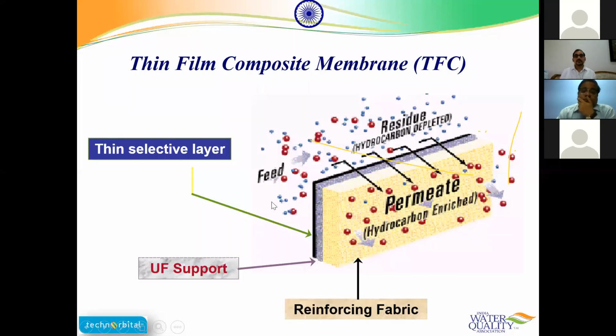Then we have a thin film composite membrane. A thin film composite or composite membrane is basically a combination of everything. We have a reinforcing fabric or non-woven fabric, then we coat it with some polymer thin film, which might be UF, ultrafiltration. Then we have a selective layer, say a polyamide layer, which gives you RO or nanofiltration. So it's a combination of 2-3 different layers. That is how the name thin film composite or composite membrane comes from.